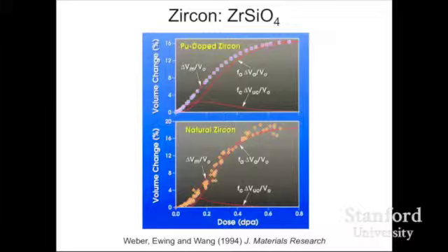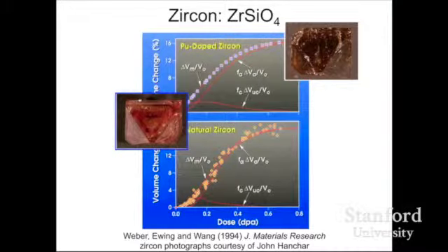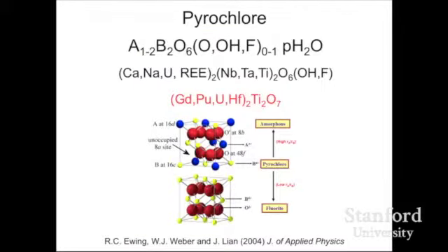Okay? So all I want to say is, one, this is pretty cool, but two, we know a lot about radiation damage accumulation in these materials. And we can see this is the zircon doped with plutonium, beautiful orange when it first is synthesized, but over a few years you can see, due to the expansion, flakes peel off and the color centers begin to dominate the color.